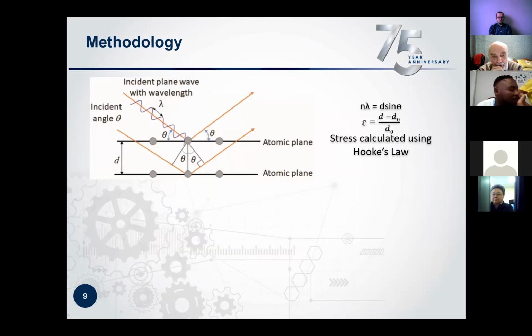In terms of the technique that we use, XRD, for those who don't know what XRD is about, we use X-rays to measure the lattice spacing between your atoms. So we use that as our strain gauge. Each material has its unique lattice spacing. So with that, after using Bragg's law, we can determine the d-spacing. If it's above the constant value, we know that the material is under tension. If it's below, then we know the material is under compression. We use Bragg's law and the sin squared psi method to determine the spacing, and from there we can calculate the stresses using Hooke's law.